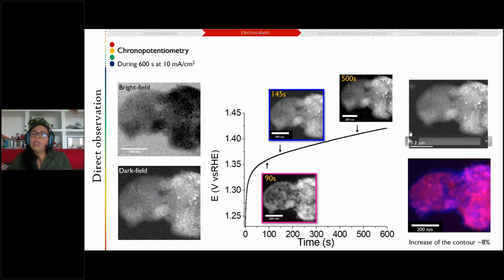And what we were able to see is that after a certain point, there is no more amorphization. The amorphous crystalline matrix remains more or less the same, and the crystalline particles remain within this amorphous matrix. Another important thing to mention here is that the electrocatalytic activity doesn't decrease because of this amorphization. It just keeps working. It keeps acting as an electrocatalyst. So this might be an activation stage of the material, which is, for example, how cobalt phosphide has been known to go through this amorphization to activate.